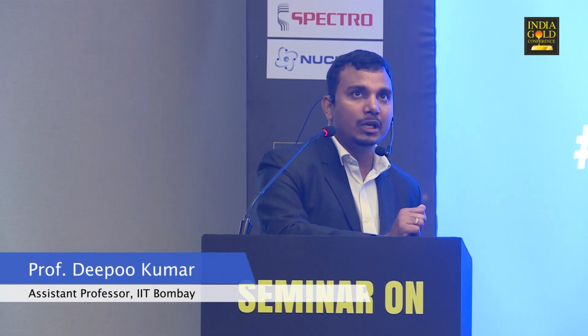For WPCB, in the metal that we get, copper has about 700 ppm of silver. ppm is parts per million, so 700 ppm will be 0.07%, which is 700 grams per ton. And gold is about 30 grams per ton.